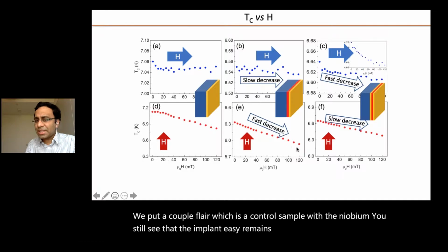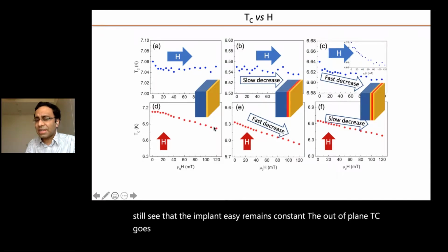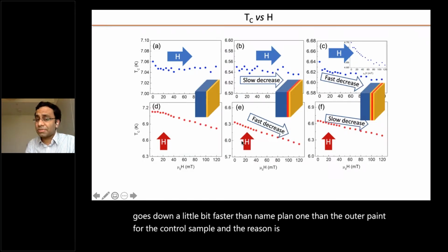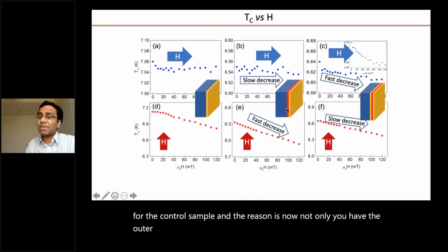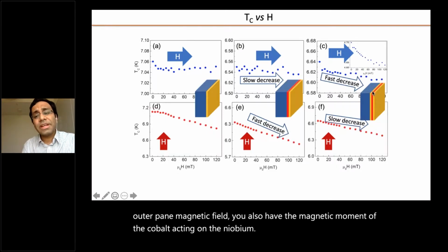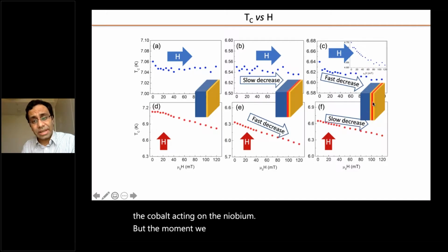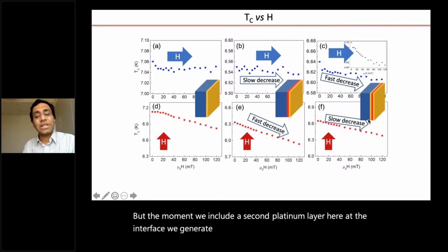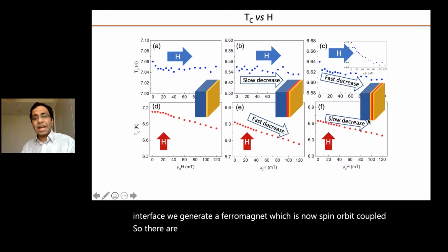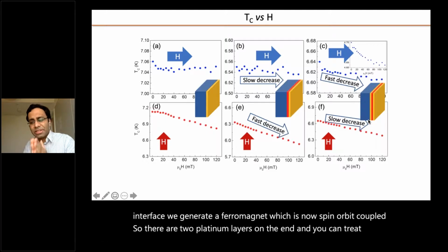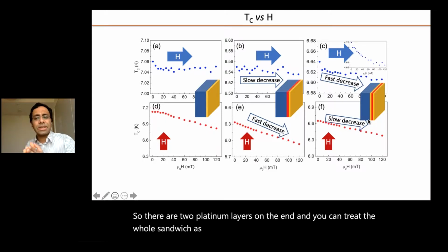The out-of-plane TC goes down a little bit faster than the in-plane one for the control sample. And the reason is now not only do you have the out-of-plane magnetic field, you also have the magnetic moment of the cobalt acting on the niobium. But the moment we include a second platinum layer here at the interface, we generate a ferromagnet which is now spin orbit coupled. So there are two platinum layers on the end, and you can treat the whole sandwich as a ferromagnet with spin orbit coupling.